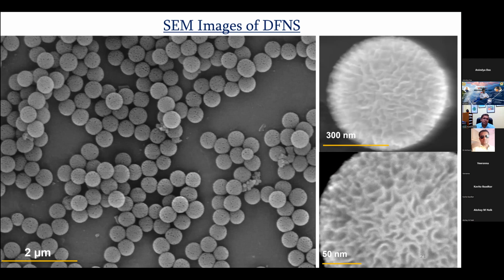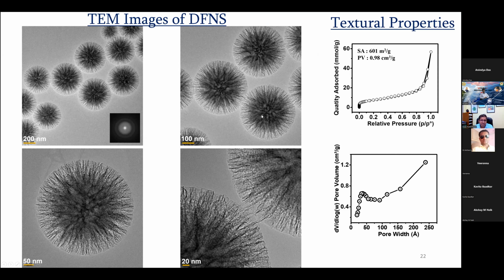So this is how the material looks like. These are electron microscopy images, scanning electron microscopy. They are very monodispersed. You see those are fibrous petals, like petals of a flower. These are transmission electron microscopy images indicating they are fibrous in nature, high surface area, around 600 square meters per gram, and a very unique pore size distribution.